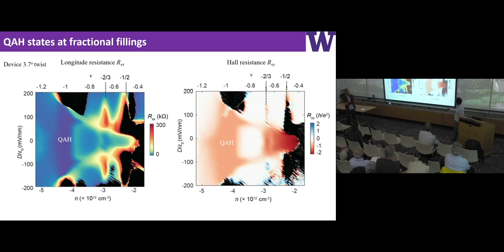If we compare these two plots, one is RXX, the other is RXY, you will see that in this particular regime, we call it the anomalous Hall metal regime. RXX is very small, and RXY is also very small. But the ratio between RXY and RXX is actually not small. The Hall angle is about 30 degrees. So we tentatively assign this phase to the anomalous Hall metal regime.